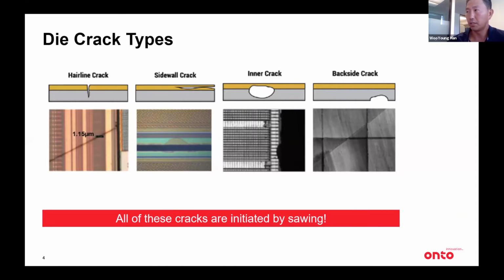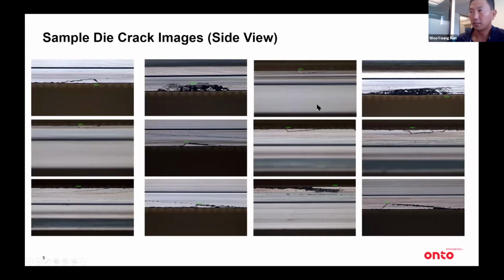As you can see, these are pretty much all initiated from the die surface. And why is that? Because a lot of these cracks are initiated by the sawing process. Okay, and here are some more images taken from the side. So these are what typical cracks and chippings look like.